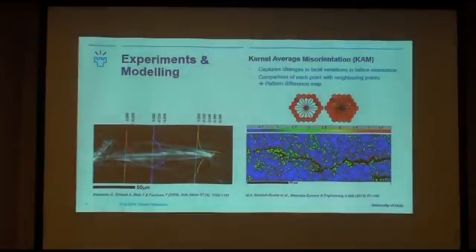So kernel average misorientation is an EBSD-based technique of measuring local variations in lattice orientation. It compares very local intra-grain data points with their neighboring points, and thus it creates a misorientation difference map. So here we have two examples from literature where we see that the deformation is concentrated around the propagated crack, and here we have another example of a formed Widmanstätten lens in a ferrite matrix, and due to this volumetric expansion it causes deformation in the interface of the ferrite matrix.